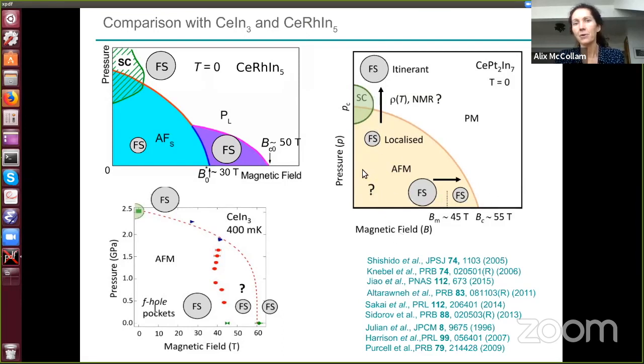With magnetic field, it's not completely clear what's happening at zero field because we can't measure the de Haas-van Alphen effect in zero field. So in ytterbium, rhodium 2, silicon 2, you can see a jump in the size of the Fermi surface by looking at a jump in the number of carriers in the Hall effect. But this measurement hasn't been done here or doesn't show anything in this material.